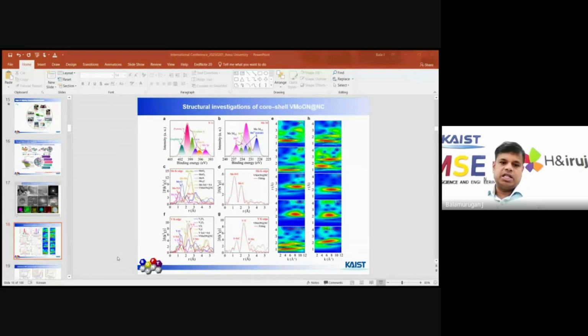For vanadium, you can see the vanadium-nitrogen bonding is very small, but vanadium-vanadium bonding is very high. From the TEM analysis, you can see the vanadium core-shell, because the metal nanoparticle is in the core-shell, but there is no vanadium single atom. This is the wavelet transform EXAFS. You can see clearly the comparison to the oxides, nitride, and carbide. Here this is the R value, and this is the K value. The R value below 2 we call metal with anion bonding, because molybdenum is bonded with nitrogen as well as carbon rather than molybdenum-molybdenum.